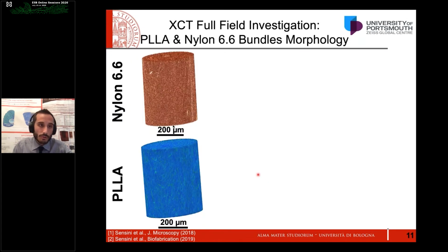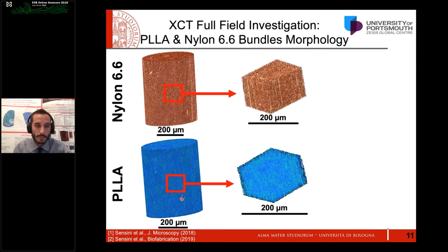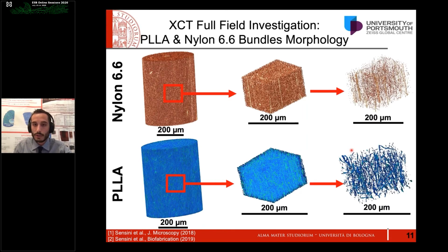The same was true also for the nylon 6,6 and the pure PLLA bundles and nanofibers, which you can see are homogeneous and made of aligned nanofibers, both on the surface and in the internal volume of our bundles. Moreover, tuning the thresholding of the scans, it's possible to see the most internal nanofibers that are also aligned.